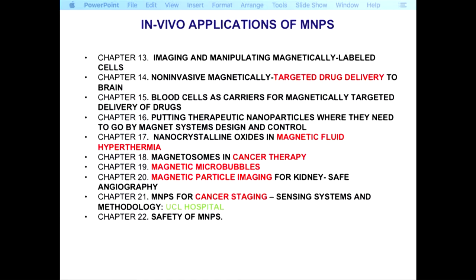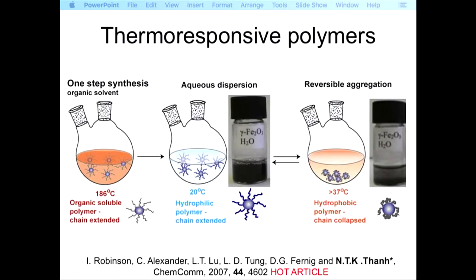For the in vivo application, as I said before, there is magnetic hyperthermia, so I just give you our effort in the field. We use a thermoresponsive polymer, so the polymer will respond to the heat. At high temperature, it disperses in hot organic solvent, like I said in the previous slide, where we do the synthesis in hot organic solvent. Then when you let the solution cool down, they change conformation and become hydrophilic.